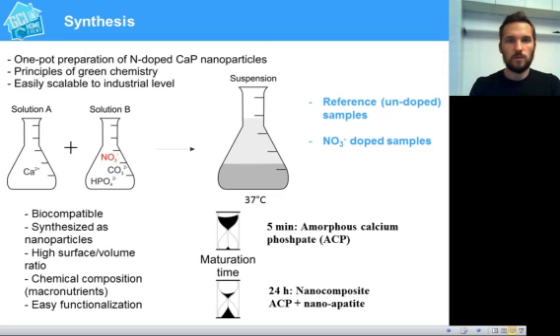The synthesis is quite simple, following the green chemistry principles, and we prepare different samples, a reference, undoped sample, and nitrate-doped samples. Starting with the two solutions with the precursors, we mix them and we obtain a suspension, and the material in the suspension is at first an amorphous phase, amorphous calcium phosphate, transforming into apatite upon maturation time.